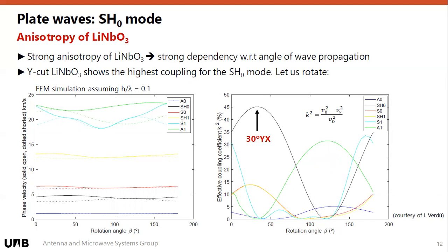So you have a lot of dependence of your wave properties with respect to the angle of wave propagation. So what we started doing here, this is a rotation angle beta, so it's an angular rotation. We are on the Y-cut, and we are moving the axis from the wafer. So the Y-cut is not going to be pointing upwards anymore, it's going to be moving this way. And in any of these cases, we're going to be propagating along the X direction. So what we can simulate is you get your thin layer, and then you simulate both fixing an open circuit condition on top.